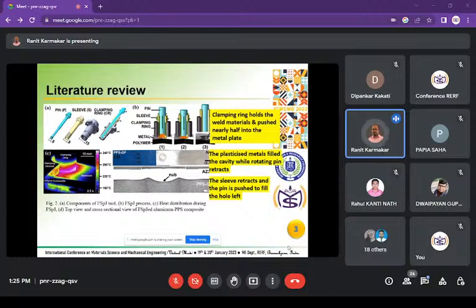And here we can show the mechanism: the clamping ring holds the weld material and pushes nearly half into the metal plate, and that plasticized material fills the cavity while the rotating pin retracts from downward to upward, and the sleeve retracts, and the pin is pushed to fill the hole left. From that we can see that a knob-like structure is formed after the welding.